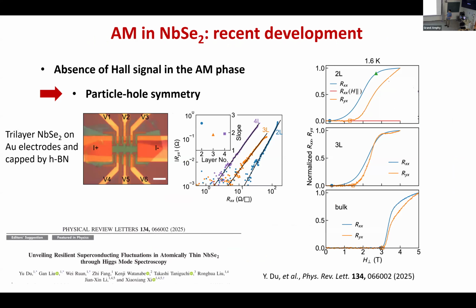So I would say that after so many years, still people are interested in this niobium diselenide setup. They just treat the system, okay, no matter the reason is either extrinsic or intrinsic, but it's there. The finite resistance state is there. Let's just measure something more. So for niobium diselenide recent work, they measured a trilayer niobium diselenide. And first of all, this was already done in amorphous films that in the anomalous metal phase, when you measure the Hall resistance, you don't see the Hall signal. So that's somehow showing that you have particle-hole symmetry in the anomalous metal phase.